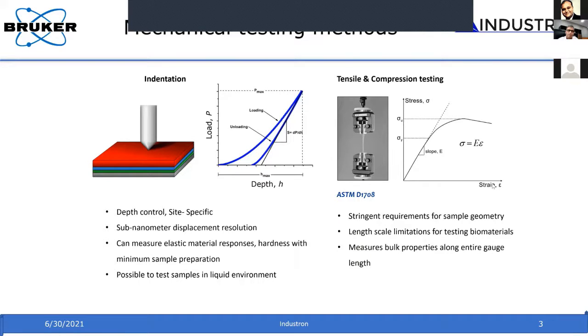So with this simple transducer structure, you can apply force, and you can do it at very, very small forces. For example, in the nanonewton regime, you can apply forces, and you can also measure displacement down to less than a nanometer. So this is what we typically use for applying force and measuring displacement with respect to nanoindentation. Okay. So in the next slide, let me see.